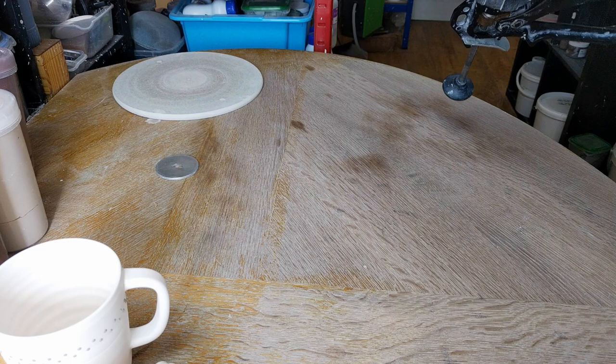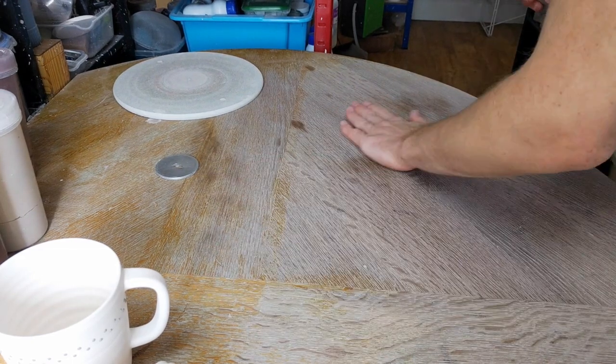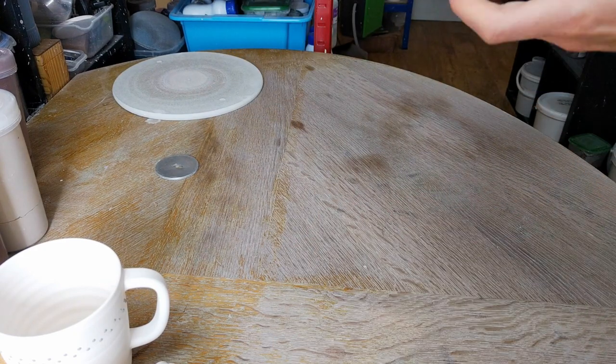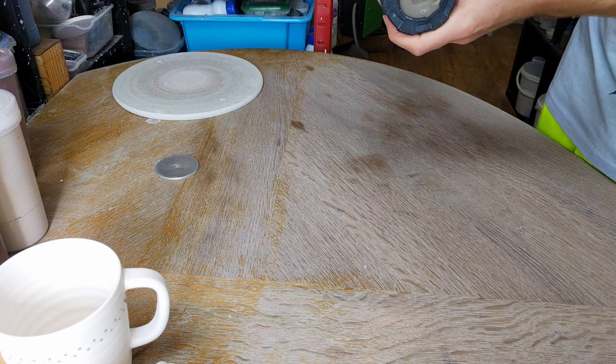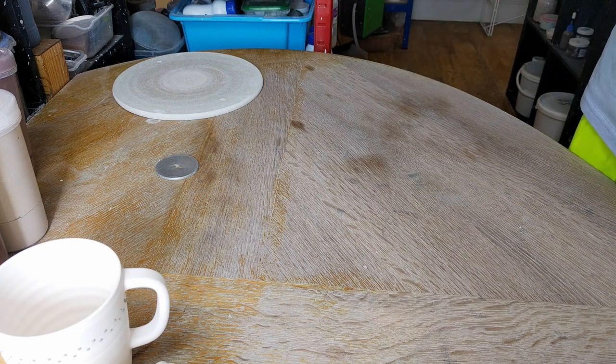I get the clay slightly wedged because it does come out better, but you don't need to. It doesn't have to be perfect, but the main thing is to get it into the extruder with as few air bubbles as possible, because after a little while you'll start getting bubbles in the extruded handle, and they're very difficult to correct.